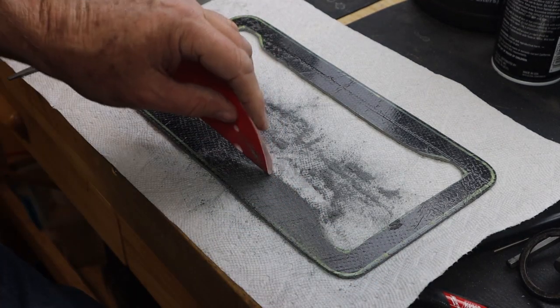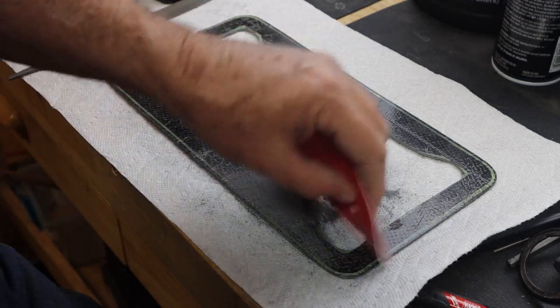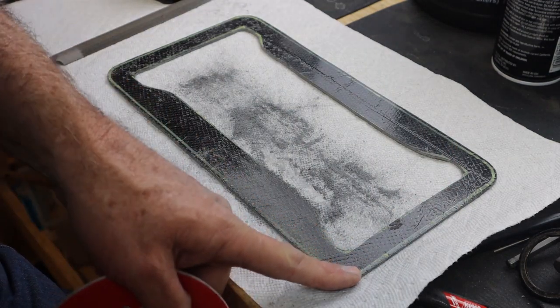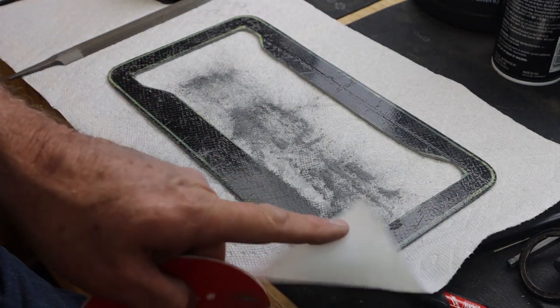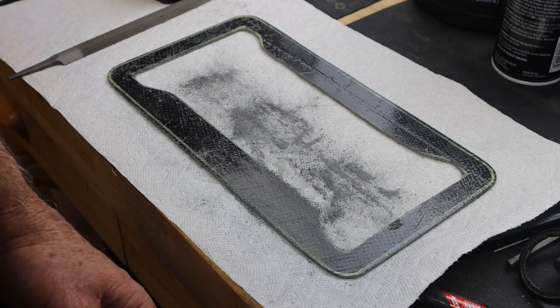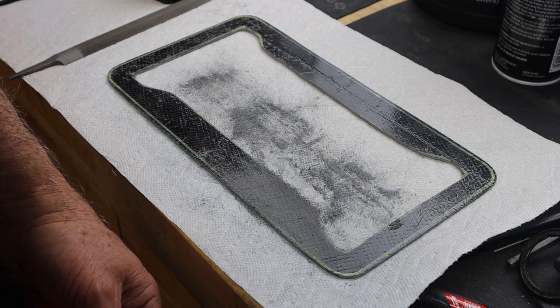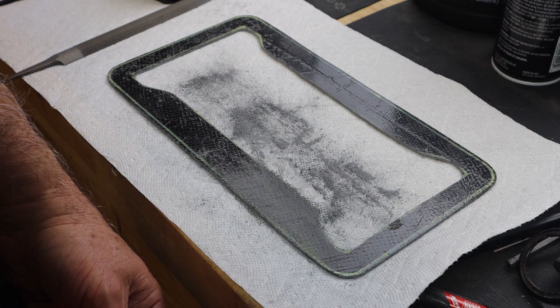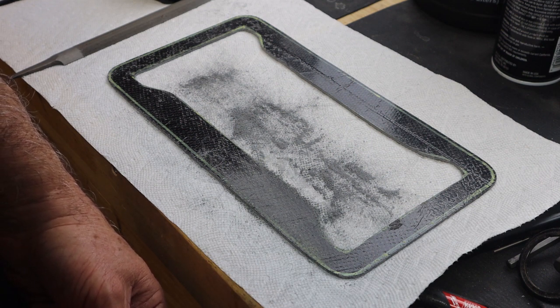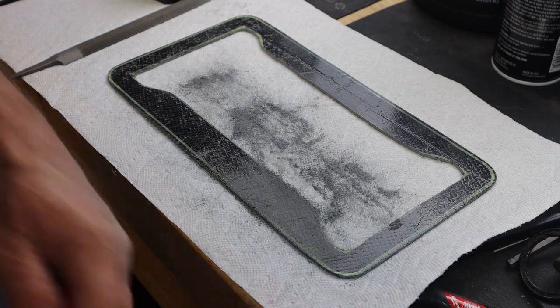What you want to do is when you're sanding the surface, you don't want to sand too deep. You don't want to sand into the weave of the carbon. What you want to do is just lightly abrade the surface so there will be enough grip for the epoxy to stick to the surface of the carbon.